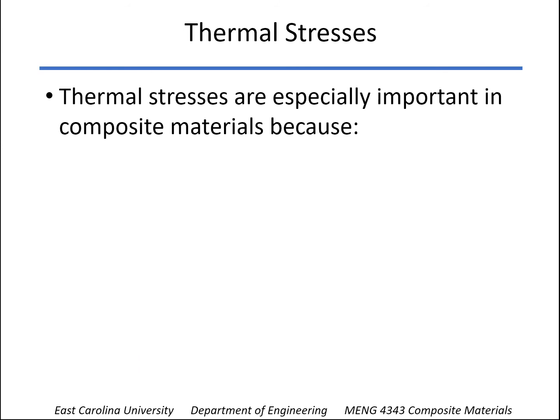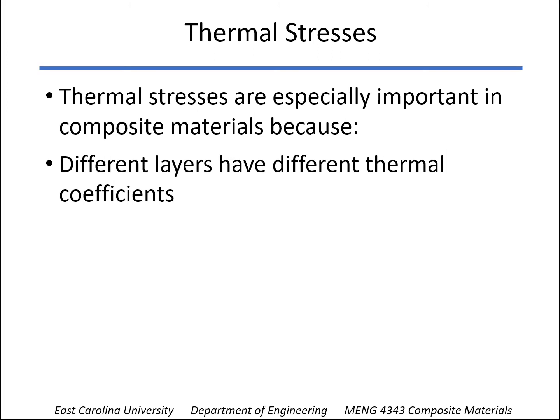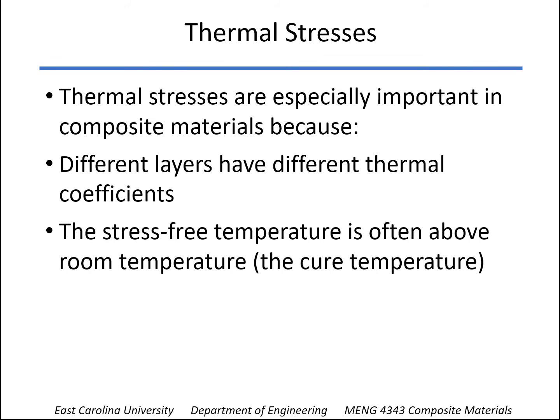Well, basically it's because you're going to have a laminate with different layers in there, and almost certainly it's going to have layers of different orientations, might even have different materials in there. But even if it's just the same material, but the angles are different, you're going to have different thermal coefficients. And what that means is when you go up to the cure temperature, if it's going to be an elevated temperature cure, the resin can flow until you get up to that cure temperature.